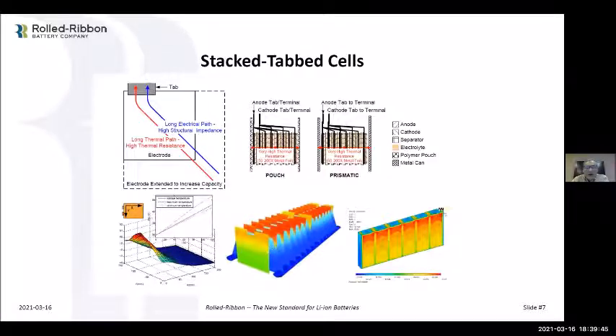Now this here is a battery module. This one has a bunch of stacked pouch cells in here. There's actually external thermal management here trying to cool this battery back down. And that's why you see all the blue down here. But it's not very effective because the hot spots are up where the welded tabs are at the top, so I'm cooling the coolest part of the cell. The hottest part gets less cooling. I can't cool the hottest part up there because this is where it's all welded together. You can't get at that, and you'll see that when I show you a module later.